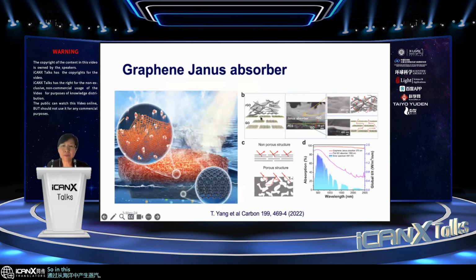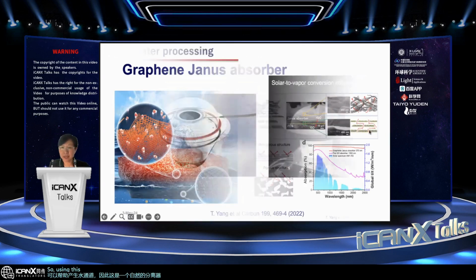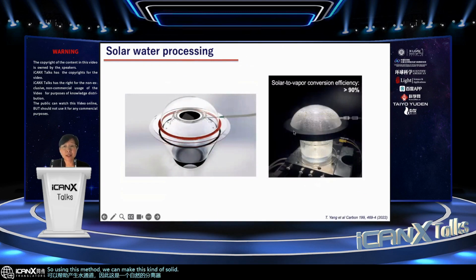In this case, we also developed this kind of Janus structure, which is made by just a single exposure of the graphene oxide. You see that at the bottom, it still maintains the graphene oxide structure, and on the top, it actually has this reduced graphene oxide structure. The reason we want this 3D and 2D structure is that the 3D structure helps the absorption of the sunlight, and the 2D structure allows the water to get through. All these gaps help to generate the water channel, and therefore this one is a natural separator for seawater. So using this method, we can make this kind of solar vapor generator.